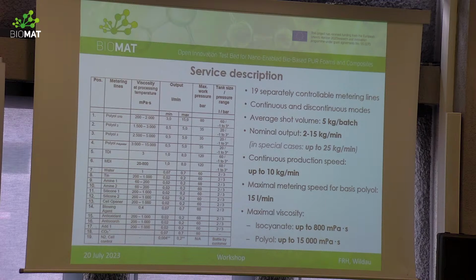With these main characteristics are average shot volumes of 5 kg per batch, and the nominal output in the range up to 15 kg per minute. For special applications, we can also achieve 25 kg per minute. And the continuous production speed, we can run at least up to 10 kg per minute.